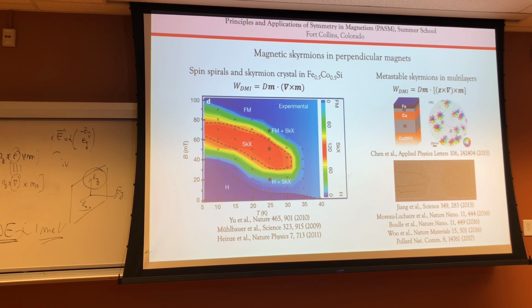So comparing quantitatively, you're going to have an order of magnitude, and actually all these methods give you the same order of magnitude, which kind of makes sense when you think about it, because you basically have exchange, spin-orbit coupling, inversion symmetry breaking at the interface. So if the potential drop at the interface has the right order of magnitude, if the orbital overlaps are kind of the same in the different methods, then you should have the same number in magnitude. However, I don't think the experimental methods are accurate enough to distinguish between the different approaches.